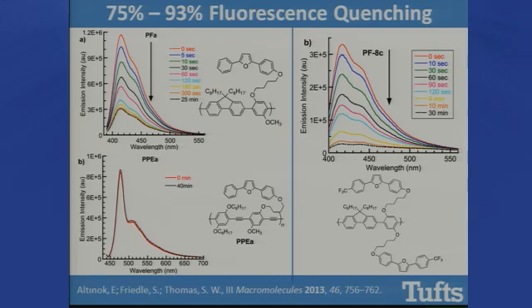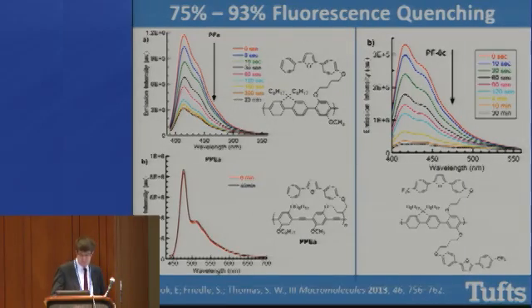Now, 75% is fine. We wanted to see if we could improve this a little bit, and we did so by designing a polymer that made these furans both better oxidative quenchers by making them more electron poor, and also doubling up. That is, we put twice as many potential quenchers per monomer unit as we did over here. Under these circumstances, although the response is somewhat slower, we see over 90% fluorescence quenching upon reaction of all the furan derivatives. This was published just recently this year.